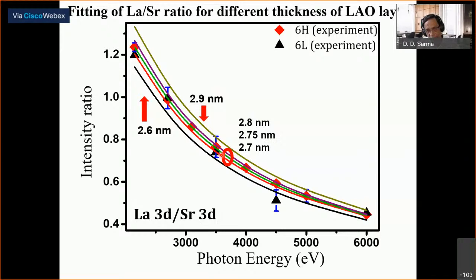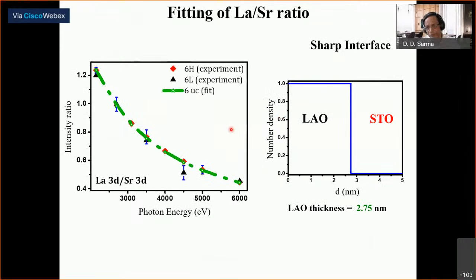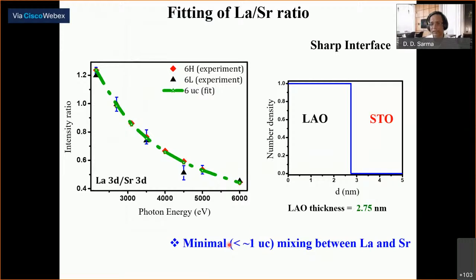All the experimental data points can be described by those which are between 2.8 and 2.7 nanometer, so plus minus 0.05 nanometer. I can pin down, and it says that I have an extremely sharp interface of LAO on top of STO, with hardly any intermixing. We put a limit of intermixing of lanthanum strontium to less than 1 unit cell, so that we can eliminate the possibility that there is intermixing giving rise to the metallic state.